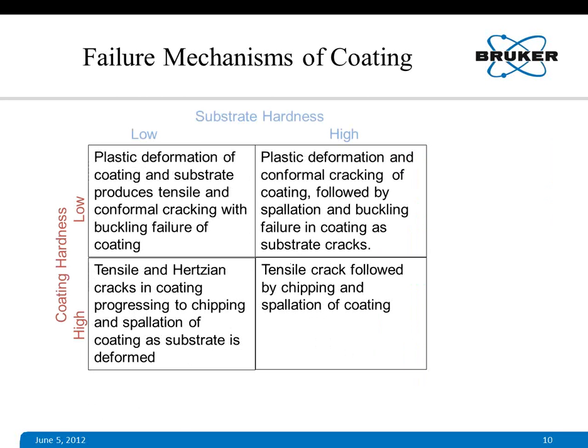Failure mechanism of coating. If we consider coating and substrate as brittle and ductile materials, they have ductile and brittle properties. There are four different types of mechanism through which coating fails. You see on the left side coating hardness, on the top, substrate hardness. When coating hardness is low and substrate hardness is low, both of them are low, you have most of the time plastic deformation of coating and substrate that produces tensile and conformal cracks, and mostly buckling failure of the coating occurs.